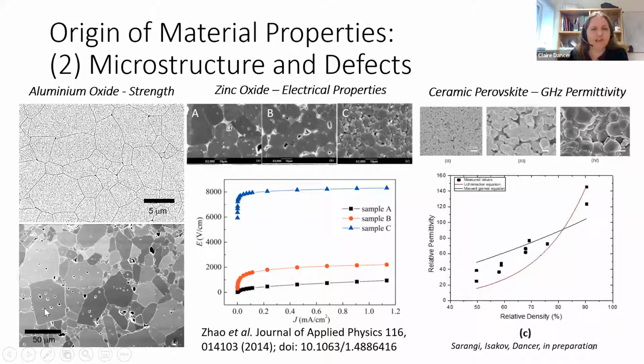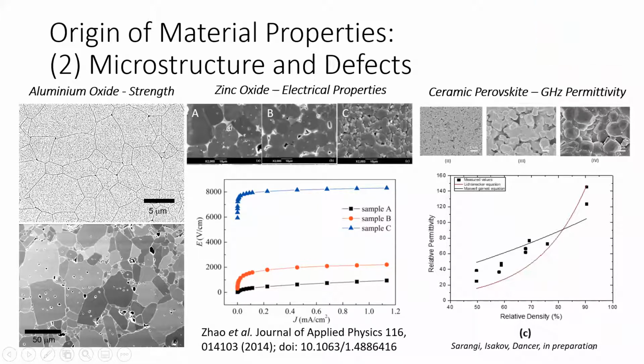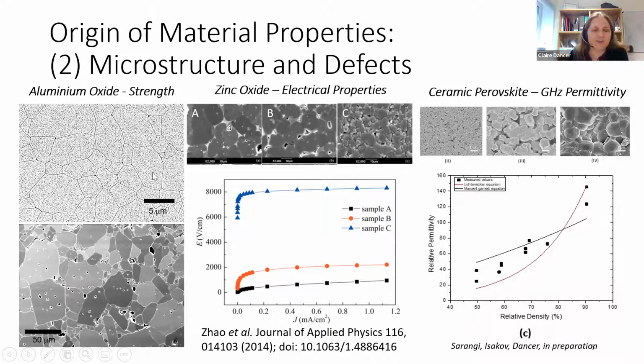And this is very, very impactful on the mechanical properties of the material. You also see quite a wide range of grain sizes, and that again can lead to more regions where defects can form, and therefore a lower fracture strength in the end. And this is indeed what we see. The top material is extremely difficult to break. The bottom material is relatively easy to break, especially after a little while in use.